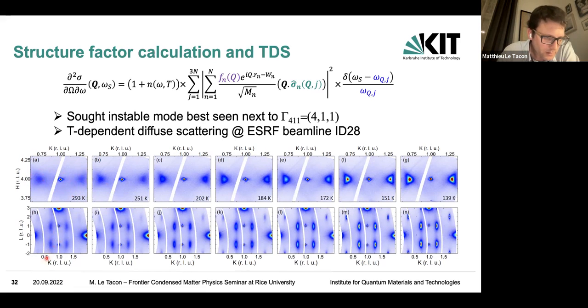If you look in the KL plane, you see this nice diffuse satellite around the Bragg reflections along the, so that would be the 4-1-L series here. And then you see this nice diffuse satellite at 0.28. As you cool down the system, the intensity of the satellite increases, and eventually it becomes as strong as that of the Bragg reflection when you're getting close to the triclinic transition.